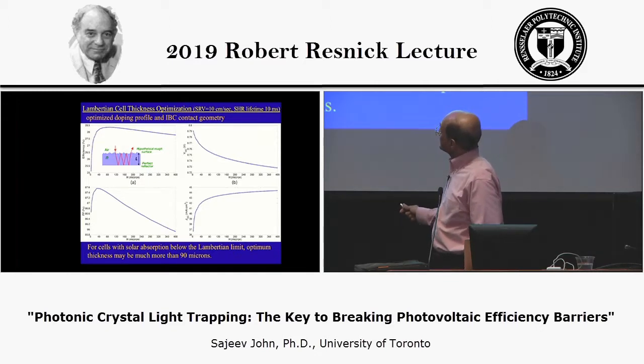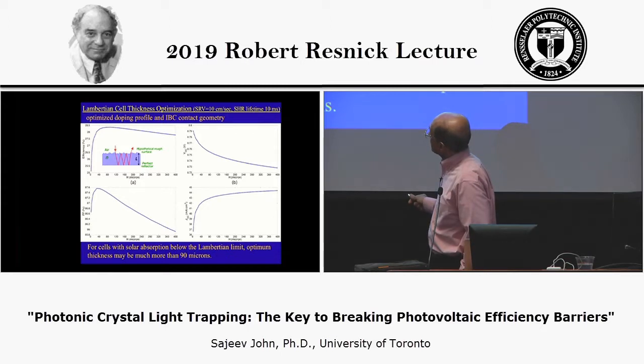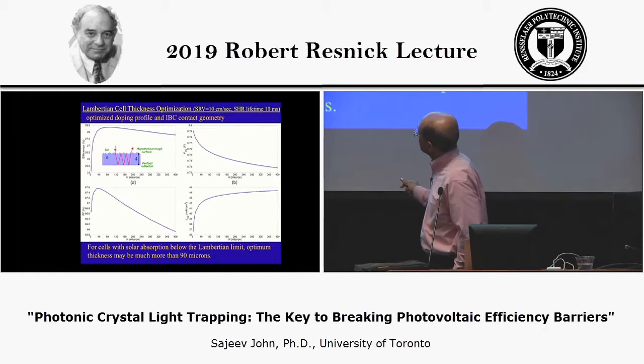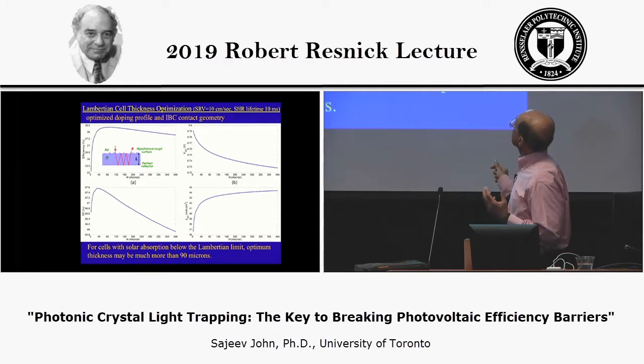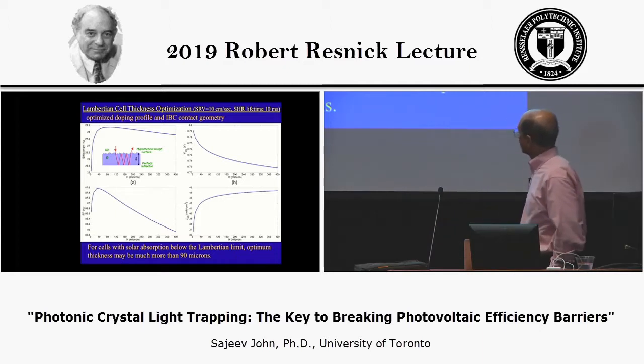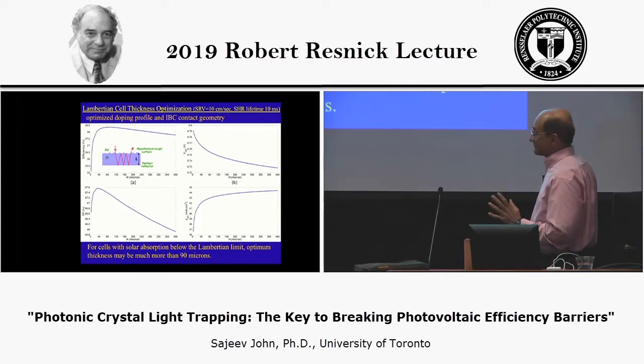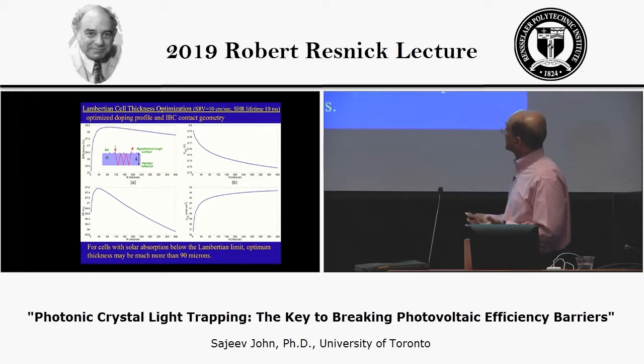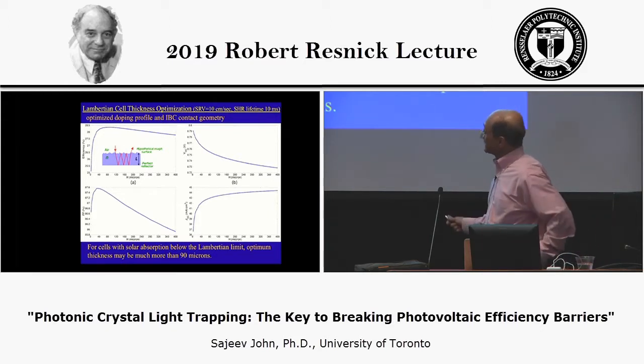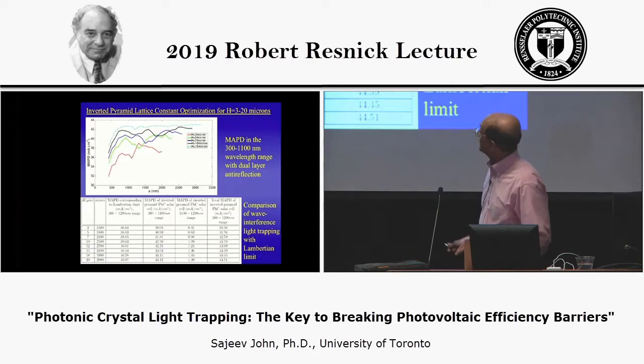So this depicts the efficiency of the cell as a function of the thickness, H or L as I'm calling it here. And so initially, if the cell is too thin, not enough light is being absorbed, but if you go to very large thicknesses, there's too much recombination, and the optimum here, including losses at the surface and this Shockley-Read-Hall lifetime, the state of the art for that is a 10 millisecond lifetime. The optimum thickness would be about 90 microns. And for cells that absorb less light than the Lambertian limit, the optimum thickness might be much more, and that's why the Kaneka cell, which set the world record, is at 165 microns. But in the case of photonic crystals, the optimum can be much less than that.